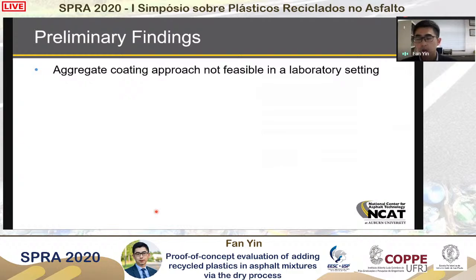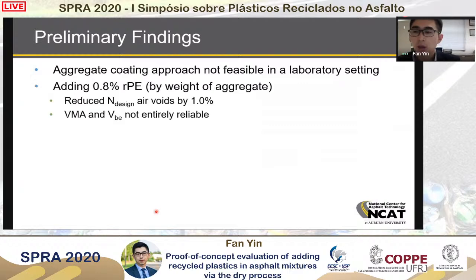Finally, a quick summary of what we found so far. We looked into the aggregate coating approach, but we were not able to duplicate what has been reported in literature. When we looked at adding 0.8% of recycled plastic, we realized it definitely reduced the air void. This is something mix designers need to be cautious about.